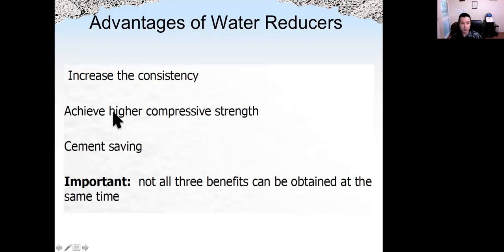So we can use water reducer to either increase the consistency. Consistency means how easy the concrete can flow. Okay, increase the slump. Or we can use it to achieve higher strength by reducing the water to cement ratio. We can also use it to reduce how much cement is used in concrete, because we can use less cement to maintain the same slump. So save the cement, save the cost, and save the environment. But not all these three benefits can be obtained at the same time. We can either increase the slump or increase the strength, or reduce the cement, but typically cannot get all three benefits at the same time.